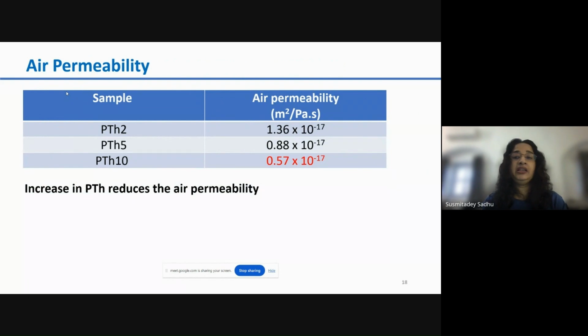We have finally studied the air permeability of the sample. So here again, we can see that with increasing loading, the permeability has reduced. So that means polythiophene is actually making the material impermeable to air.